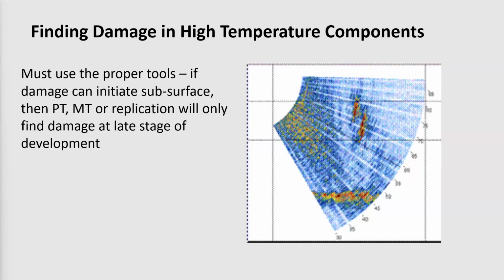And so to find the damage, first of all, you have to use the proper tools. If you're in a situation where there's potential that the damage could start subsurface, then surface inspection techniques like dye penetrant testing, magnetic particle testing, or metallographic replication are going to be of very limited value, because they typically won't find the damage until it's very far advanced. And so in those cases, it's going to be essential to use one of the volumetric techniques like ultrasonics or like radiography.